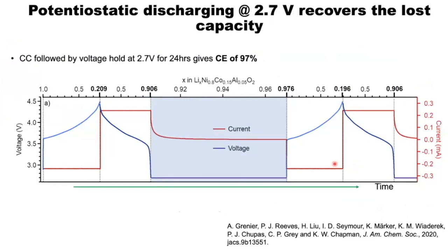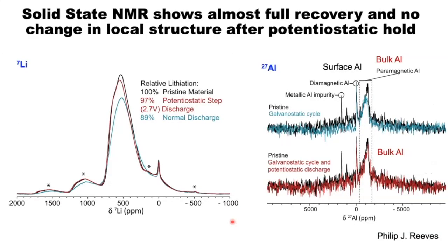So if you do a constant current charge and then discharge, you can see that you come back to about 0.9 lithium back into the material. But if you actually hold it at 2.7 volts for, in this case, 24 hours, we can really almost get back to 97% of the capacity. And this is the work done by Antonin Grenier. And we can then look at this process by NMR and show the same thing.